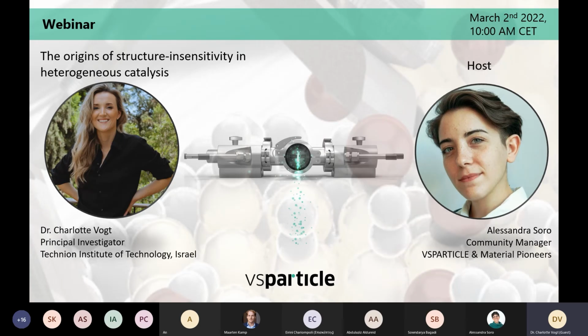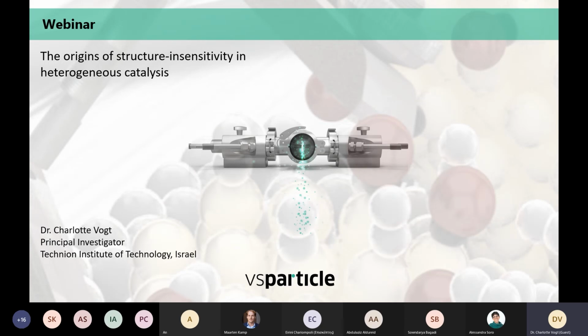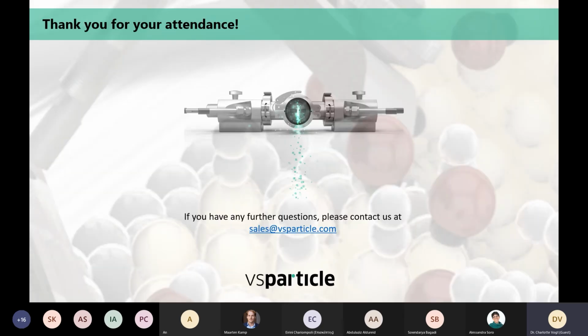Do you have strategies to limit carbon deposition in the ETEM? Good question. Ours was all empirical, and what I've noticed is that the most important thing is to reduce the flow, to have a non-carbonaceous reductive atmosphere. So we used hydrogen and we heated it up, and we just kept it there for a significant amount of time. Even if we measured images at lower temperatures, like room temperature, before reducing, afterwards we would still see some carbon deposition. It wasn't as bad as when we would measure while we were reducing.